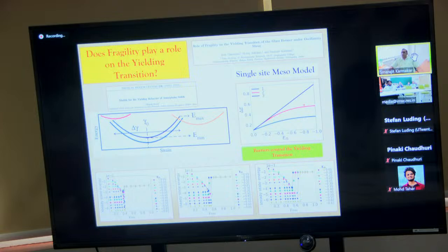We use this information in the mean field single site model and repeat the calculation to produce the steady state of oscillatory shear. We find that when you take a liquid whose barrier doesn't grow beyond a certain value as you do better and better annealing, you get a diagram where the yield point does not move anymore. But if you take a glass modeled by this black curve, where the energy barrier grows with annealing history, then you get a phase diagram where you can clearly see that the yield point systematically moves to higher and higher strain. This suggests that while modeling these kinds of materials at a coarse grain length scale, one must include this information about barriers and how they evolve with your annealing protocol. Although this is a single site model, so talking about shear bands in this is nearly impossible.